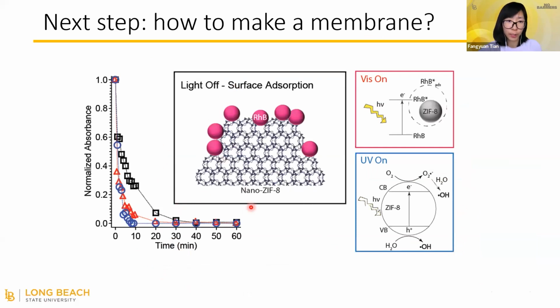And we're trying to figure out what the mechanism is for this ZIF-8 absorbing of Rhodamine B. Based on our studies, we found that in the dark condition, ZIF-8 has lots of functional groups on the surface, including carboxylate, carbonates, hydroxide, and secondary amine. They could absorb or trap those Rhodamine B on the surface with a stronger interaction.